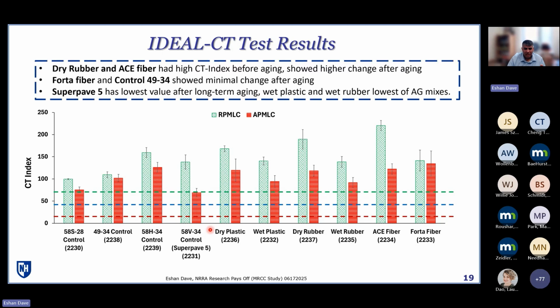But what we can in general see is that, once again, that control material without any type of modification had the lowest CT index values, especially unaged or reheated. And with aging, it also had a low value. The only other mix that actually had a very low value, or even lower than control, was Super Pave 5, even though it used that 58V minus 34 binder. It did not really have that high of a value.